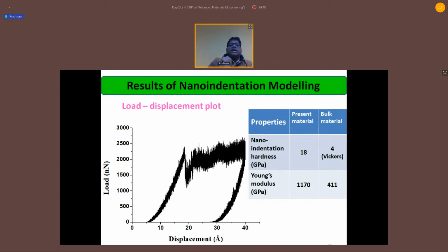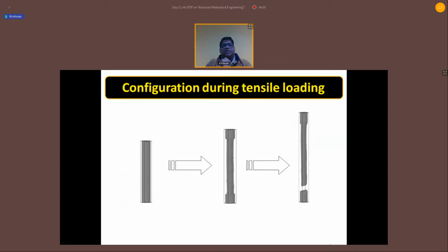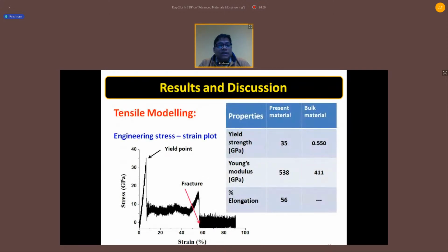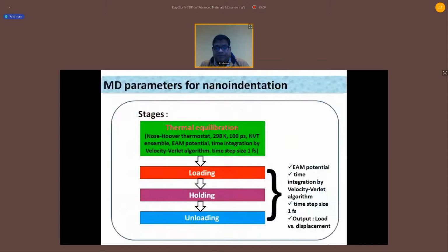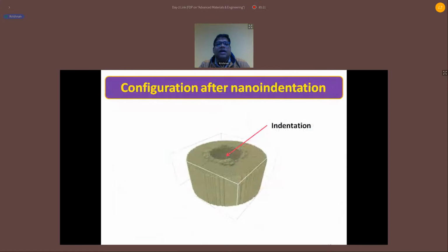And this is the configuration: the initial configuration, the intermediate configuration, and after that the final configuration after fracture. And this is on the tensile modeling. From the tensile test stress-strain curve and plot, we have calculated the yield strength, Young modulus, and the percent elongation. And this is the configuration using OVITO. The middle portion is the indentation, where we can indent actually. Using OVITO, we can find out the configuration.